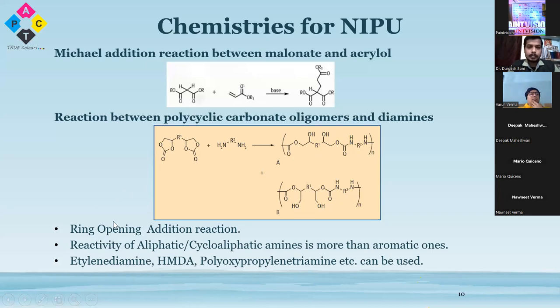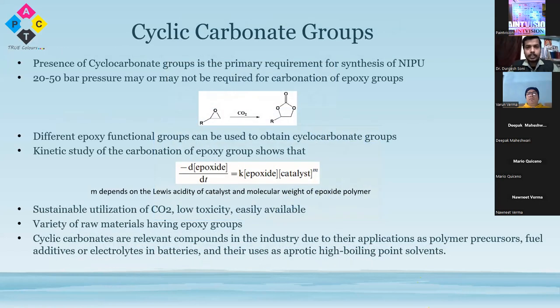So this is basically a ring opening addition reaction, and the cyclic carbonate oligomers may be aliphatic or aromatic depending upon the raw material we select for the epoxy groups. And the curing agent may be ethylene diamine, hexamethylene diamine, or any aliphatic or aromatic diamine. So the cyclic carbonate group is the most important for the synthesis of non-isocyanate polyurethane.